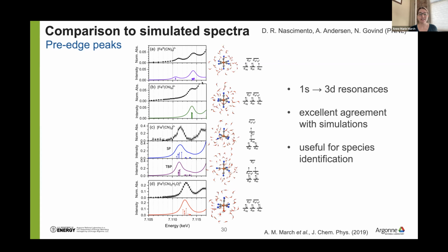And so their simulations are the solid lines. Our measurements are the black dots, and they agree beautifully. So I have different species involved here. The iron 3 we measured just statically by itself. Then there's ferrocyanide with one pre-edge peak. And then we have the pentacoordinated species, which can have two different geometries, a square pyramidal geometry and a trigonal bipyramidal geometry. And the pre-edge features here are very, very similar. We can't distinguish with our measurements, but overall it matches very well. And then the aquated species matches very well. So this was pretty cool.